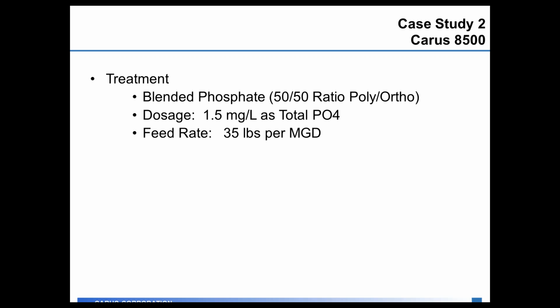So the product they picked for this water quality was a blended phosphate, and they picked a 50-50 blend of poly to ortho. Their dosage for the system was 1.5 milligrams per liter as total phosphate, so that would give them 0.75 as ortho and 0.75 as poly, and that feed rate translated to 35 pounds of the product per million gallons treated.